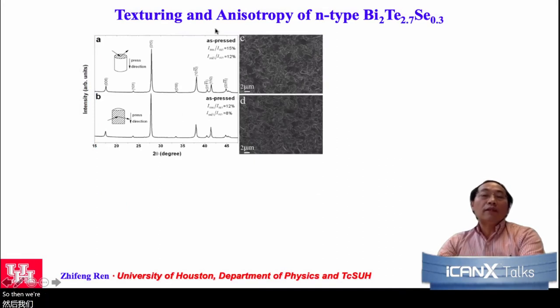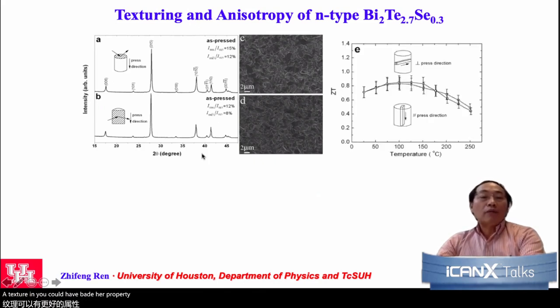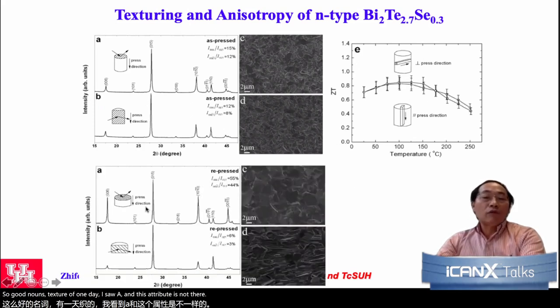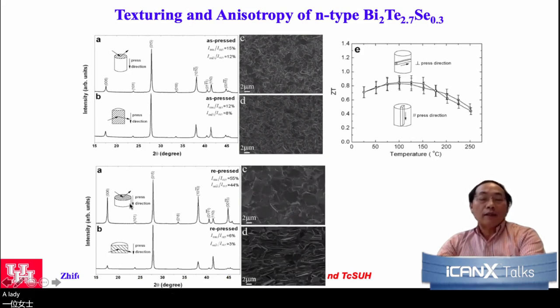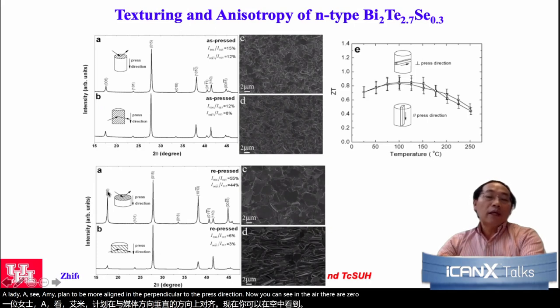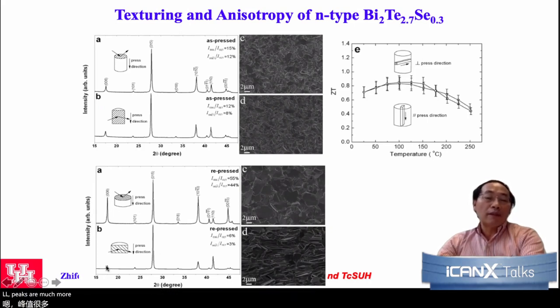So then we were thinking, since this material is a layered material, if you further texture it, you could have better property. And that's what we did. For the non-textured one, the anisotropy is not there. For the textured one, as you can see, if you do another hot press, letting the AB plane be more aligned perpendicular to the press direction, now you can see those (00l) peaks are much more prominent than in the other direction. Which means you have much texturing, like the microstructure here shows you.